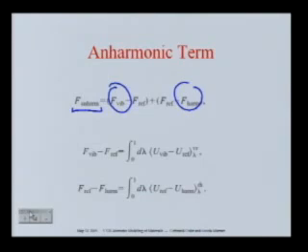So with all this formalism, what one is able to do at the end is calculate free energy differences, in which the fundamental components are calculating the phonon frequency of your system, in this case specifically for a solid, that gives you the first step in the vibrational free energy, and is nothing else than a density functional perturbation theory calculation.